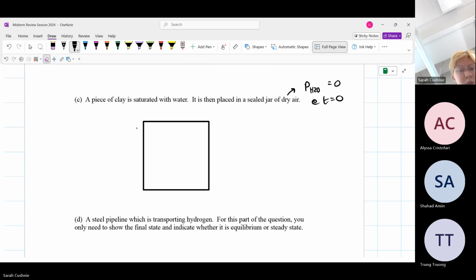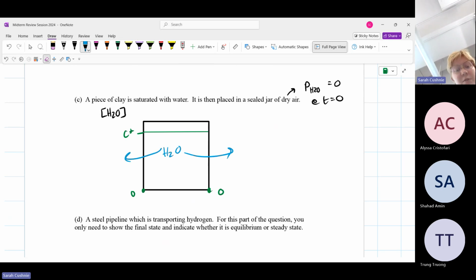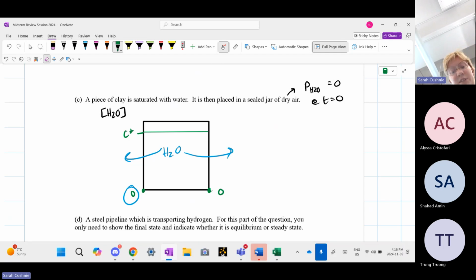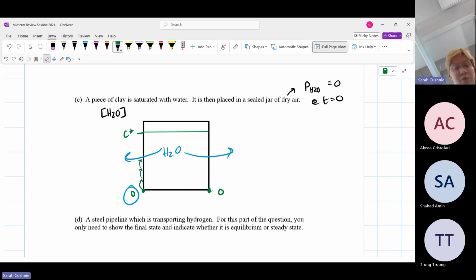So once again, we start with just our initial conditions. If we're plotting the concentration of water, we start at something that's saturated, right? I'm going to call that C star. And we start with this all the way through the clay. But now we put it in a sealed jar of dry air where it's down to 0. So over time, we're going to start diffusing all that water that's in the clay into the air around. But as we do that, the pressure on the outside, or the relative concentration that will be caused by the outside pressure, is no longer going to stay at 0 because now we're getting that water vapor in the air. So it's going to shift upwards and upwards and upwards until you reach some sort of equilibrium between the clay and the air in the jar.